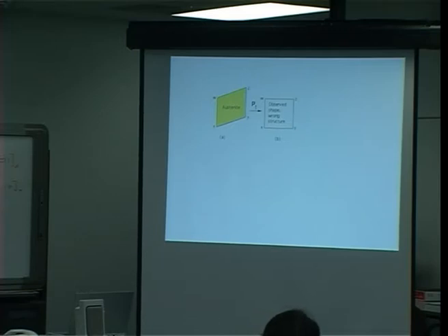Is that zero? No, they are on different planes. So one shear is happening on this plane, one shear on this plane. Is there any line which is left unchanged by the combination? The common one. No, you see, the shear will leave every line in this plane unchanged. This shear will leave every line in this plane unchanged. So at the intersection, there will be a line which is completely undistorted and unrotated by both deformations. So a combination of two invariant plane strains, say P1 and P2,